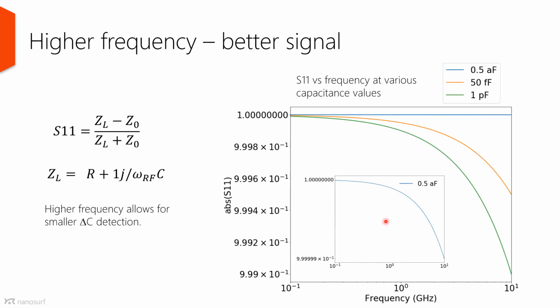Now let's continue a bit more with the formulas and try to analyze them a bit. One consequence of the impedance being a function of frequency is that the changes in the S11 parameter, while changing the capacitance, are also frequency dependent. The higher the operating frequency is, the higher is the change in S11, and therefore the smaller is the smallest detectable change in the capacitance. In the microwave world, going to the higher frequency ranges is expensive and requires significant changes in the electronics, but within a given technology that defines the range, it is always best to go for the highest possible frequency.